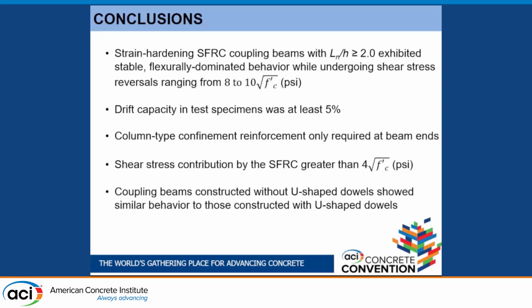Whether you have U-dowels or not at the ends, it seems that did not lead to any meaningful difference in behavior. So as long as you have enough longitudinal steel crossing the interface, or the beam-wall interface, to have enough shear friction, you should be fine in terms of not having any sort of sliding failure prematurely.